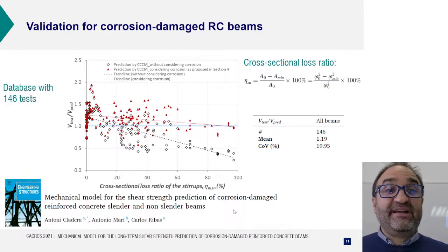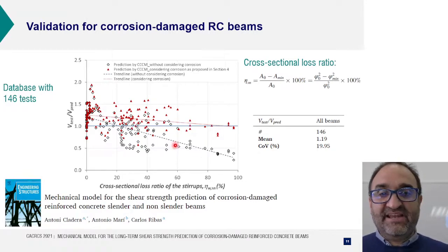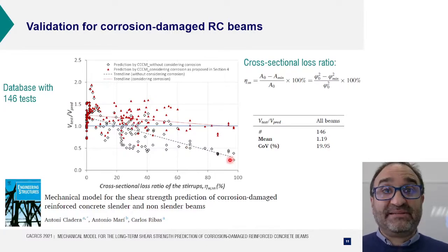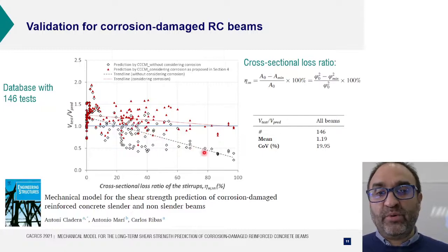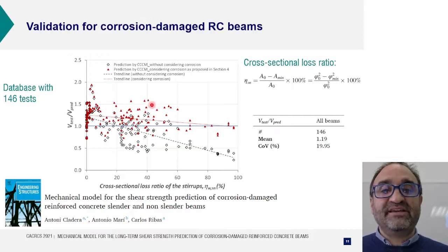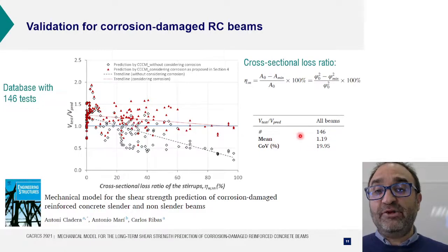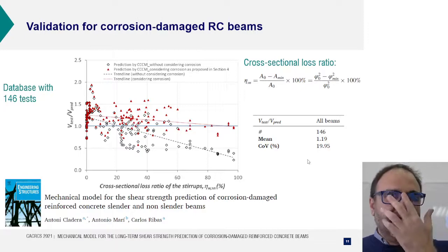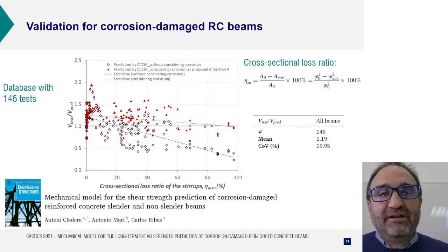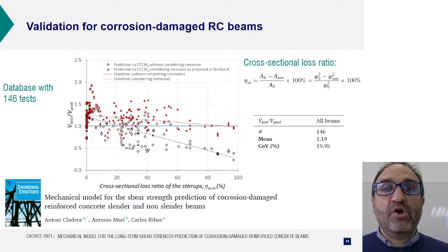Well, we use a database with 146 tests, and you can see here with these black rhombuses that if we do not adapt the model to consider the corrosion, we will get unsafe results, especially unsafe for heavily corroded beams. But the red triangles show you the correlation of the empirical shear strength and the predicted strength considering the corrosion. In fact, for these beams, the mean value was 1.19 with a coefficient of variation lower than 20%.